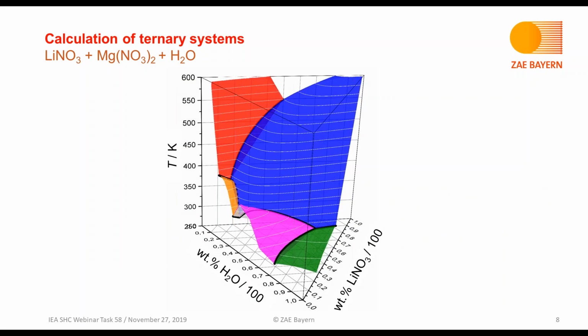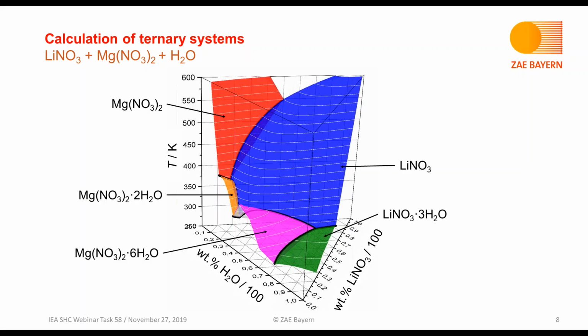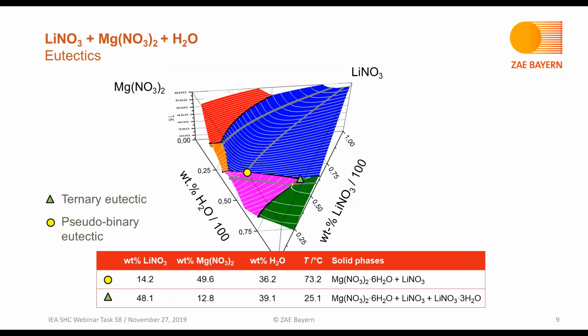In the case of ternary systems, the example given here is lithium nitrate and magnesium nitrate and water. And now we have different liquidus surfaces in this diagram. You see the base of the diagram, the composition triangle, and in the vertical direction, the temperature is plotted. And here are the different solid phases that occur in the system, the two anhydrates and then several salt hydrates. What is interesting in terms of PCM development is the location of the ternary eutectics.